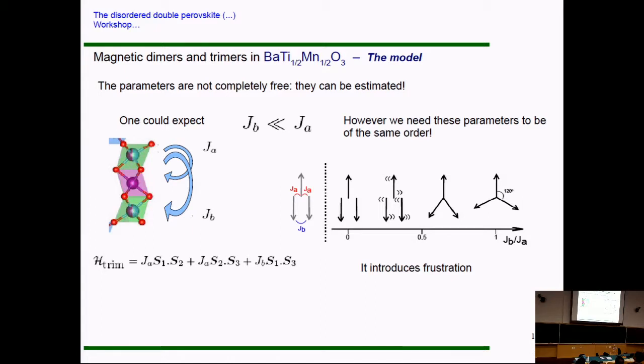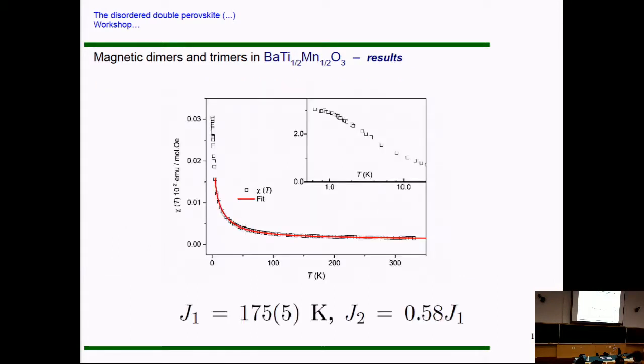And they need to be comparable in order to introduce some sort of frustration in the system that will lower the magnetic response, and the magnetic response becomes more or less compatible with what we get from experiments, right? So we did that, and this is the kind of result we got, right? This is just to understand, in a very broad view, what the magnetism is at high temperature. Of course, when you see that, it immediately raises the question, because we are fitting here